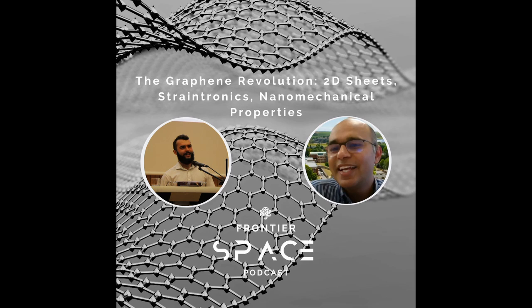Maybe you have seen some regions of the battery swell. It's because the lithium ions are absorbed in the graphite, the surface area increases, and it swells. In the case of graphene, it can adjust more, or provide a better response, but they're not using plain graphene, they're using a graphene aerogel, which is a very porous structure. Then it can accommodate more lithium ions, and that's why the performance of the overall battery will be very high.